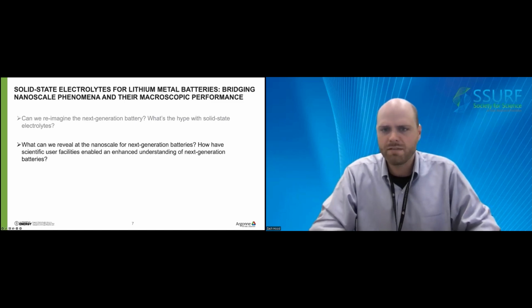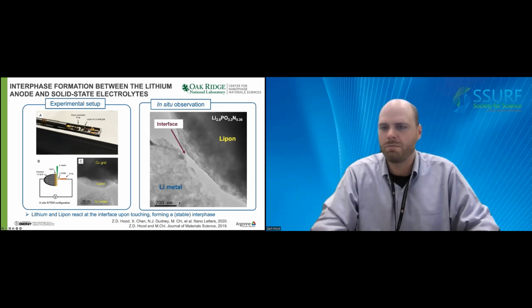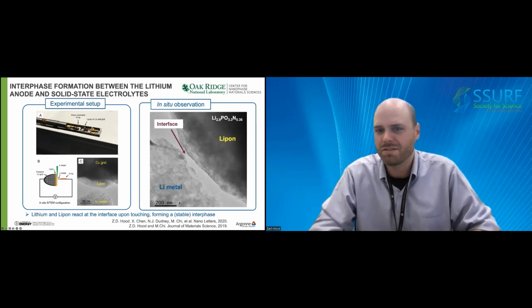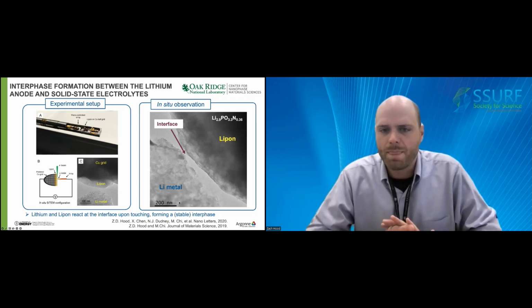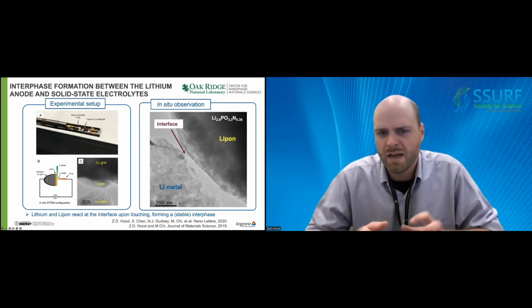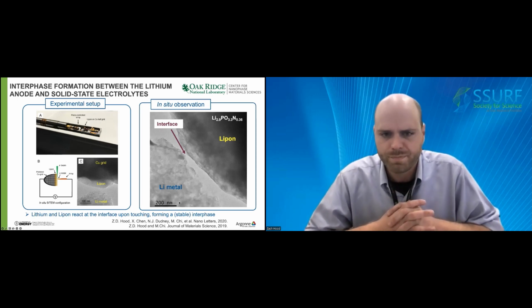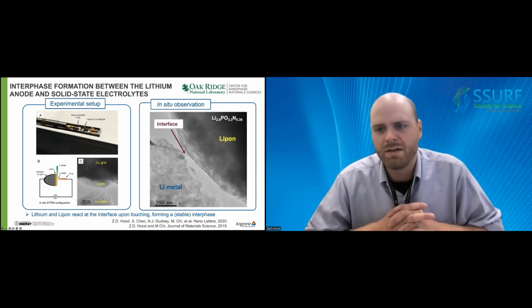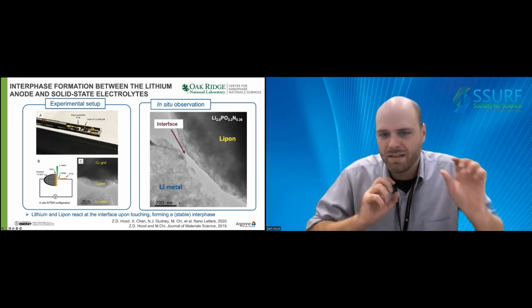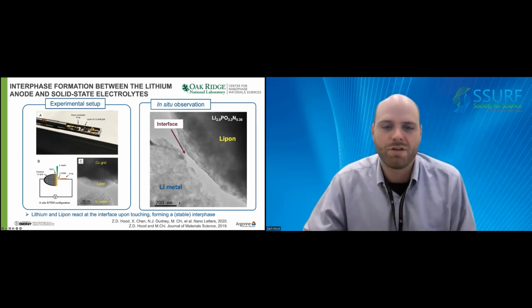So in my first example, I'd like to introduce the concept of interface formation between lithium metal anodes and solid-state electrolytes by highlighting some of our recent work that our team completed on the solid-state electrolyte lithium phosphorus oxynitride, known as LiPON. Although LiPON has a relatively low ionic conductivity, LiPON-based microbatteries have been shown to cycle over 10,000 times with lithium metal anodes. And the lithium metal anodes are generally less than around a micron in thickness when they start. However, there's much to really be learned about this interface between the lithium metal anode and the solid-state electrolyte for us to better improve materials for these next generation batteries.